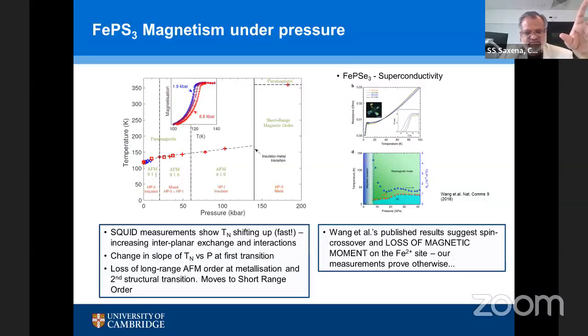So this result was slightly controversial because previous people using XMCD work had presented the idea that the system is not magnetic. And I think this is why I was showing you the iron results before, that often people, when they look for just long-range order and don't find it, tend to classify something as non-magnetic. But in terms of short-range order and magnetic fluctuations, those of us who are more interested in quantum states often look for it specifically, and in some cases we find it, as in here.